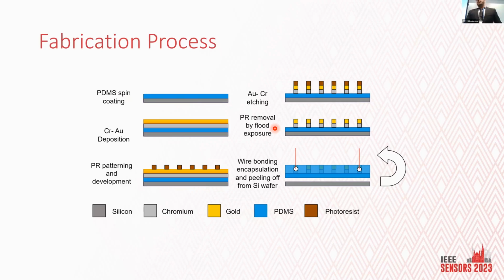So one problem you will also face while reading the literature about PDMS is that it is very bad with organic solvents such as acetone, IPA, and all. So we have completely avoided acetone, IPA, and those kinds of chemicals, and we came up with this fabrication process. After that, we connected the interconnecting wires, which are enameled copper wire, and after that I encapsulated this sensor using PDMS itself.